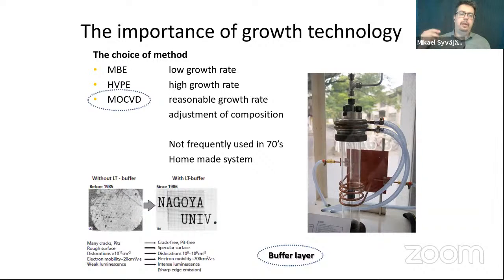It has a reasonable growth rate, and you can adjust the composition so you can get the right nitride composition to get the blue light from the nitrides. But it was not frequently used in the 70s. So what they did at Meijo University was to make a homemade system. This is a picture of a homemade system. I think this is either the original or the replica of that system. I took this picture when I visited them. It was for growing the high quality material, and then they made the buffer layer and so on to have quality.